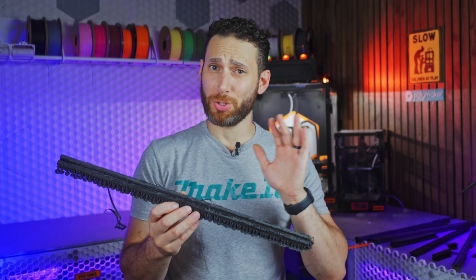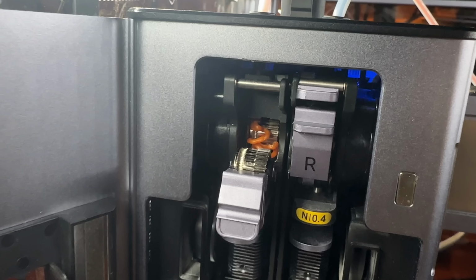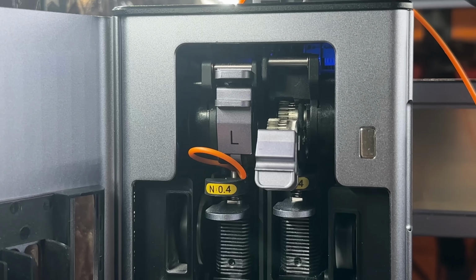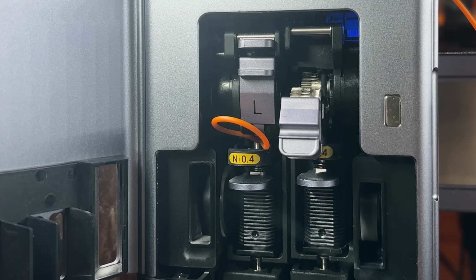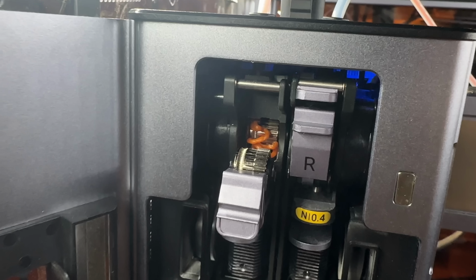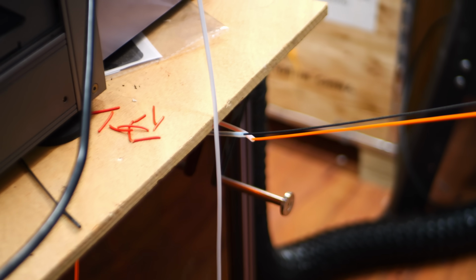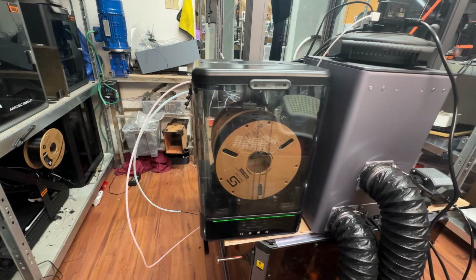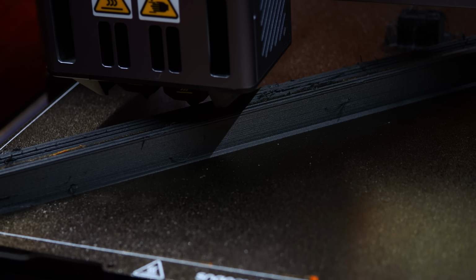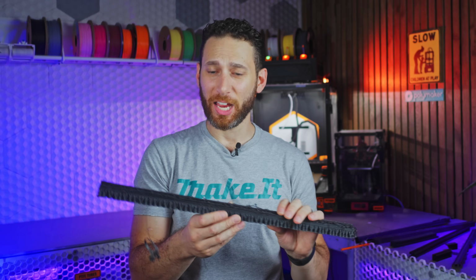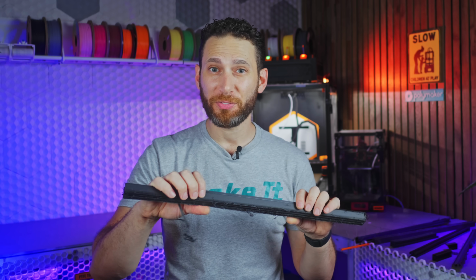For all its great traits and qualities, the Snapmaker Artisan has an extruder that is basically wholly incompatible with flexible filaments. I tried multiple times with multiple different setups to try and reduce the amount of friction on the filament, and it just was not happening. Plus, the high friction of the carbon fiber filament in the long Bowden tube seems to have caused some under extrusion throughout the entire print.